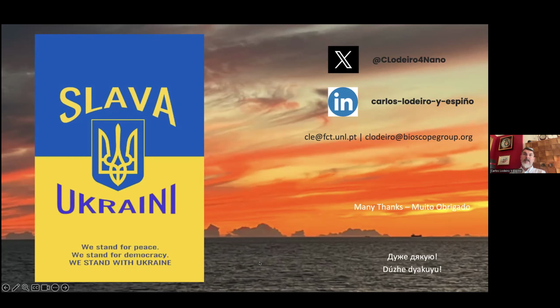The stability compared with the spherical nanoparticles: of course, we have spherical nanoparticles that can be used 3-4 years after if the stabilizer prevents the aggregation. But in comparison with these anisotropic ones, which have better properties, especially for biomedical or biological applications, up to 6 months is okay. One year maximum we are studying now, and the results are pretty nice.